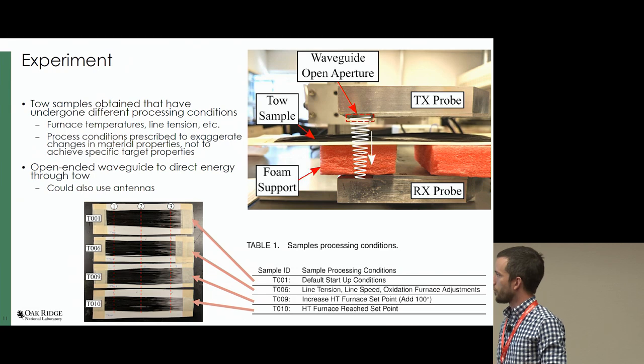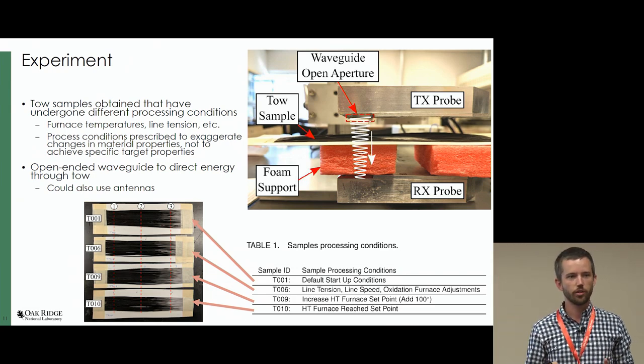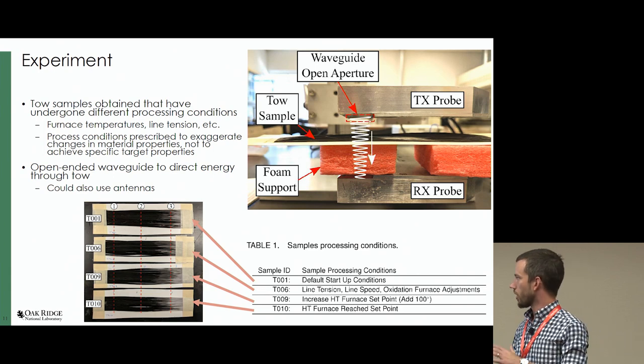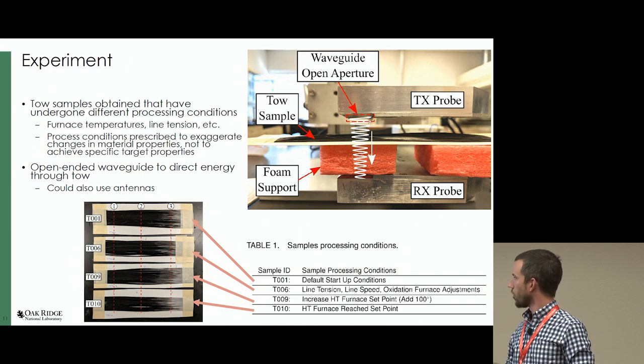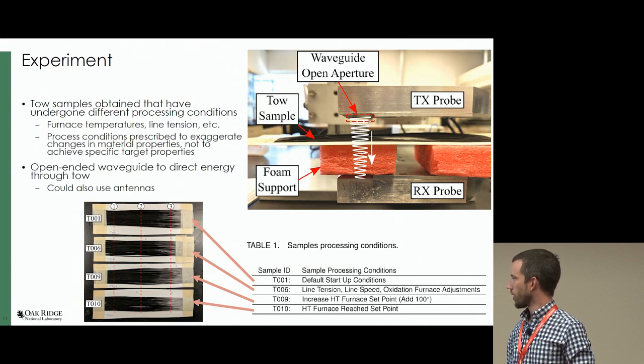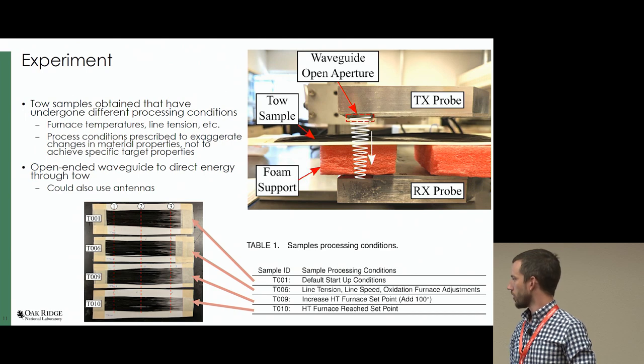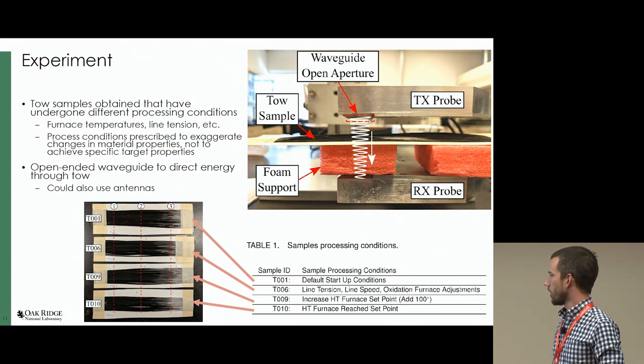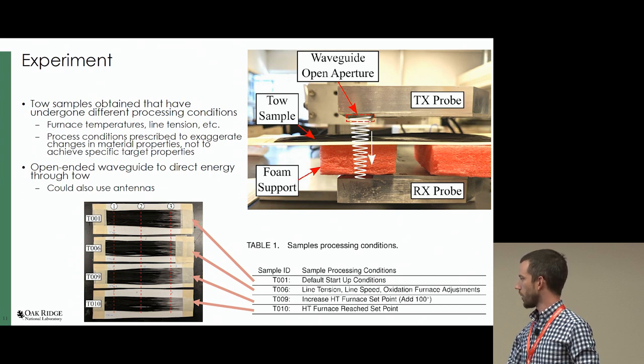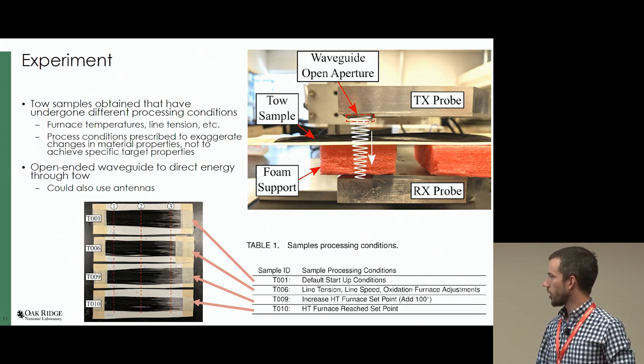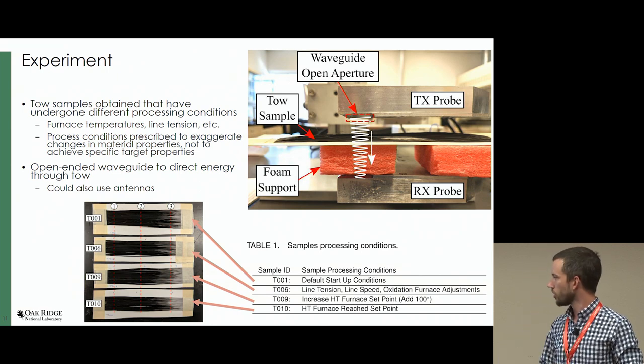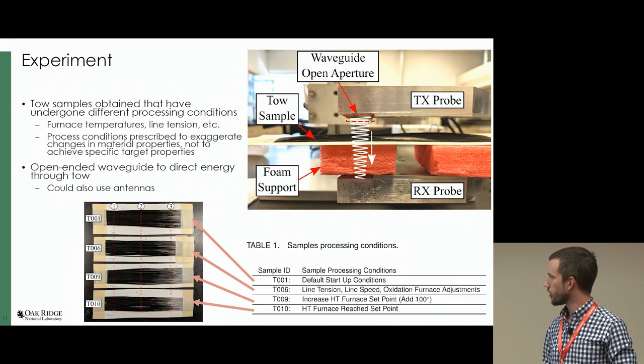For the experiment, they ran the process line with exaggerated process variables to make the conductivity change a lot. We have two waveguide probes — we just direct the energy through the tow and measure the attenuation. We had four samples: T1, T6, T9, and T10. T1 was when we started up the process; T6 was some adjustments to line tension and line speed; T9 had the furnace adjusted by 100 degrees; and T10 is when it reached that set point. Looking at the carbon fiber samples visually, you can't really see anything — they look identical — so that's why we're using these measurements to see where the differences lie.